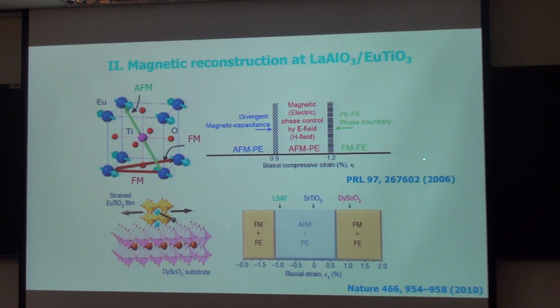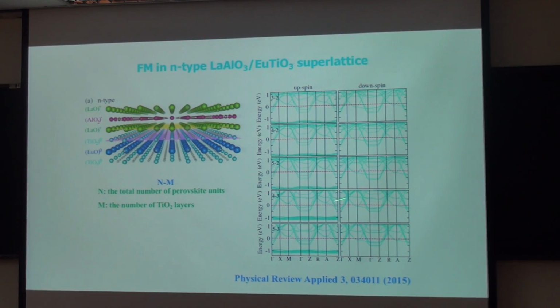Their predictions were realized several years later experimentally, where scientists grew the ETO on different substrates and realized ferromagnetic and ferroelectric order simultaneously. Here, by introducing superlattice structure, we have realized a charge transfer induced antiferromagnetic to ferromagnetic transition.